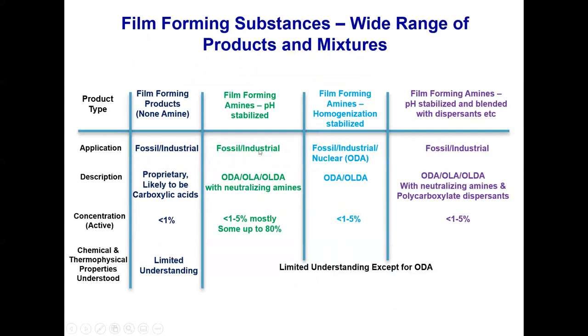Now you can see right here, there's a wide range of FFS products and mixtures. You can see across the top some general categories: film forming products, non-amine, film forming amines which are pH stabilized, film forming amines which are homogenization stabilized, and the final one, pH stabilized and blended with some other compounds such as dispersants. Applications are all across the fossil and the industrial regime, and there's some description here. Very loose descriptions, where these are all a combination of these three different active ingredients, and then the proprietary ones are essentially not known.